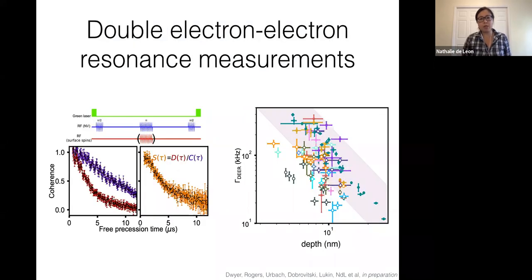So our main workhorse for being able to interrogate these spins is something called double electron-electron resonance. Schematically, this is very simple. You basically do a Hahn echo sequence on the NV center that consists of a pi over 2 pulse, a pi pulse, and a pi over 2 pulse to read out the spin. And this should refocus dephasing from quasi-static noise in the bath.